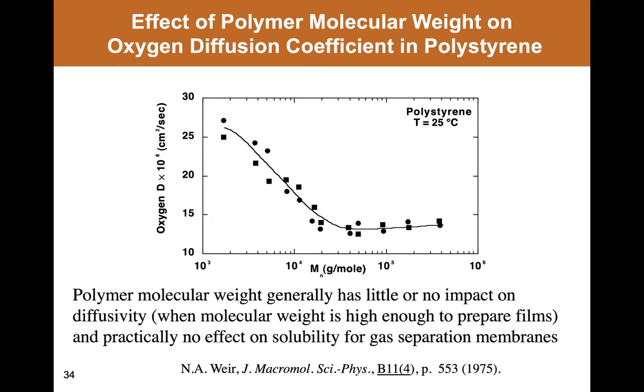However, by the time most polymers get to a molecular weight where it is possible to make mechanically stable freestanding films, you're out of this regime where the transport properties depend on molecular weight, and you're over in this regime where the transport properties are independent of molecular weight. And so this is why in a lot of the literature you don't see people emphasizing molecular weight, or in some cases even reporting the molecular weight of the polymer that they're studying, because the molecular weights are generally always in a range where molecular weight has almost no impact on transport properties.